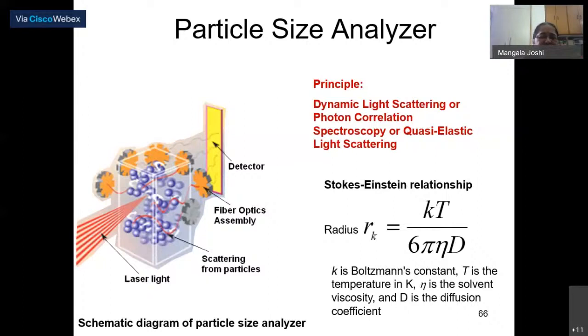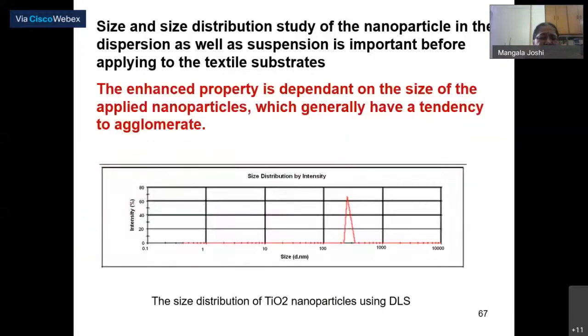And it basically uses the Stokes-Einstein relationship where k is the Boltzmann constant, T is the temperature in kelvins, and eta is the solvent viscosity. So you have to take care, you can't use very highly concentrated samples here. Otherwise, the movement will become difficult. And D is the diffusion constant. So D is measured by the movement. Bigger particles move slowly and smaller particles move fast.